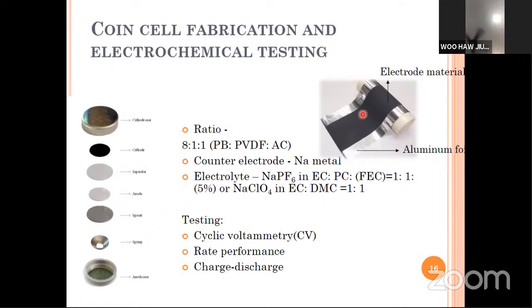And then we sandwich this cathode material with the electrolyte, NaPF6 in EC, PC and FEC 1:1 and 5%. Another type of electrolyte that we tested is NaClO4 in EC and DMC ratio 1:1. This is a half cell test, so we use sodium foil as the anode material. And we sent it for testing, running cyclic voltammetry, rate performance, and charge discharge.